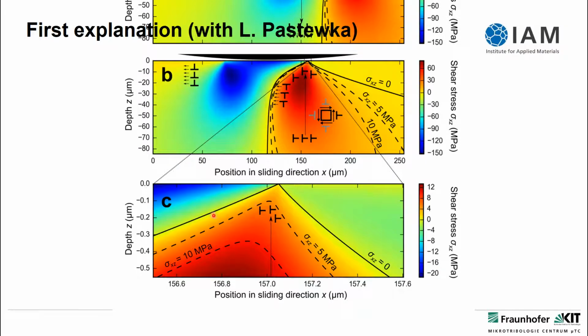Because if you now see where, for example, an iso shear stress line for 5 megapascal is, you can see that the dislocations will not move completely to the surface because you need a finite stress to move a dislocation. If you look in literature, old literature from the 60s and 70s, you'll find that you need, in really well-annealed copper, a minimum shear stress to move a dislocation of around 5 megapascals. That's why we plot here the 5 and 10 megapascal iso lines.